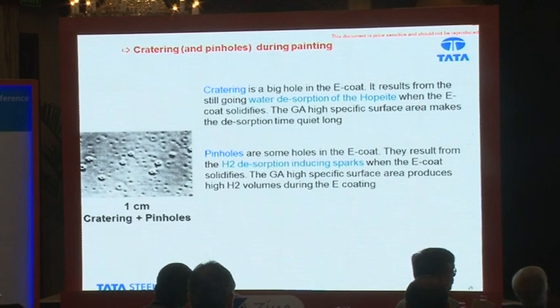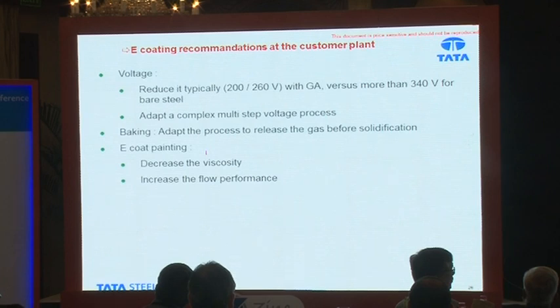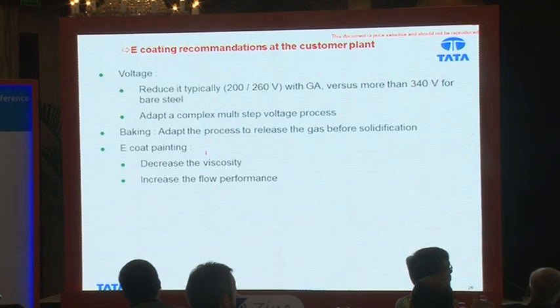This is one particular problem which is very typical of galvanneal. It is called cratering and pinholes. It happens during the e-coating or the ED paint, and the answer to this lies in reducing the voltage. The voltage, or the potential difference by which the ED paint is deposited onto the body, has to be reduced. The solution is that the automaker, if he knows this, can easily use this material by having typically 200 to 260 volts against 340 volts for bare steel.